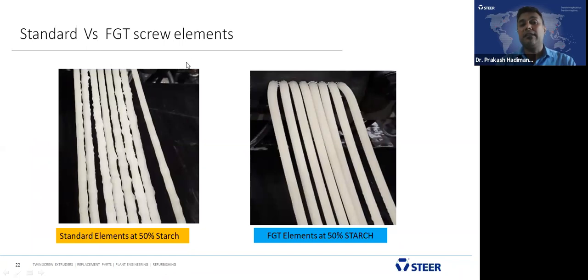When we use standard and FGT technology, we observed with standard technology, after 50% of starch loading, the rough surface and also the foaming, which means the starch started gelatinizing inside the extruder. That shows the foaming starts and is difficult to control in the standard technology. The same product we use for FGT technology. You see here, we have a smooth surface and well dispersed strands, smoother in the surface, and no rough surface and no foaming we observed by using FGT technology. Also, we have achieved higher throughput and higher RPM.